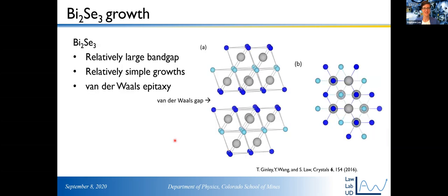Okay, so just, I'm in material science now, so a brief mention of which material we're going to look at. We're going to look at bismuth selenide. It has a relatively large band gap of a whopping 0.3 eV. It's actually not that large, but it's big for a topological insulator. It's pretty easy to grow. It's a binary compound. You grow it by van der Waals epitaxy. Here's its crystal structure. I have a lot of thoughts about how to grow these materials. If people are interested, I can talk about it later. I took all the growth slides out to try to not take too long.